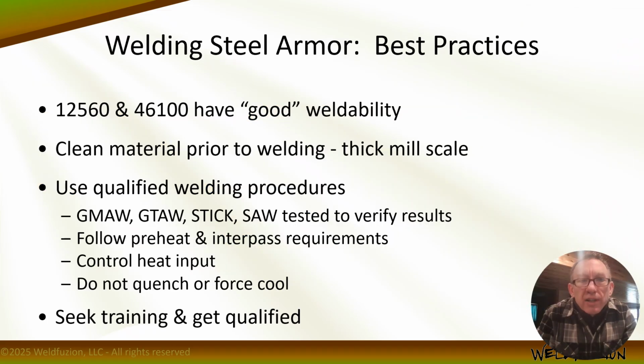Both 12560 and 46100 armor have good weldability by industry standards, and success is largely centered on following best practices. Right, so we want to clean the material prior to welding. Both have thick mill scale from production and processing, and this is a source of contamination, garbage, and trash that can be introduced into the weld area. Remove the mill scale and reduce the chance of garbage contaminating your welds.